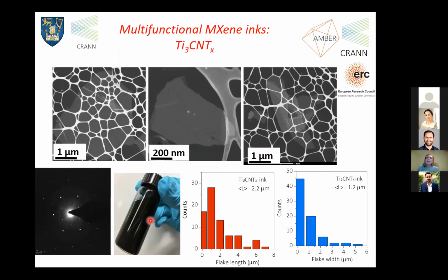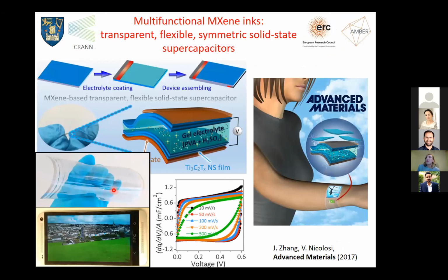So this is the type of material that you get after a simple handshake in water, where you get extremely large flakes, all monolayers, and they are structurally very defect-free and very, very good. They are extremely conductive, electrically conductive, and mechanically very robust. So for us, they really tick a lot of boxes of processability so that we can follow up with our applications. So the first application we did with MXenes, we partnered with Yuri Gogotsi on this, was really to use them to make transparent, flexible, symmetric, all solid state supercapacitors.